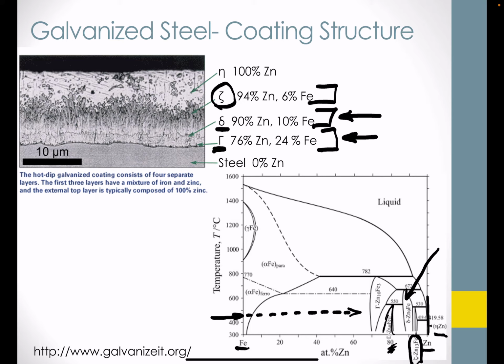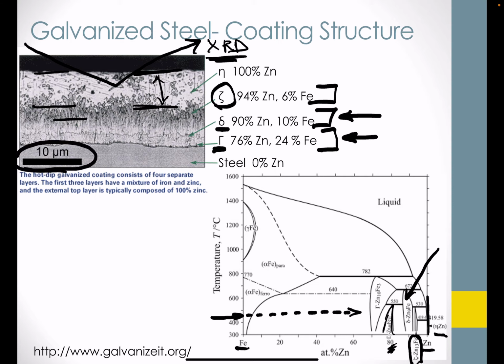micrograph. Further, other techniques that may be surface sensitive or have certain penetration depth may interrogate only the zinc, or depending on the thickness of this eta phase, may only show just pure zinc. So consider this diagram when you're reflecting on any X-ray diffraction data to consider whether or not the XRD data will show characterization of just the topmost layer or perhaps layers below, given its penetration depth and the scale shown here in this image.